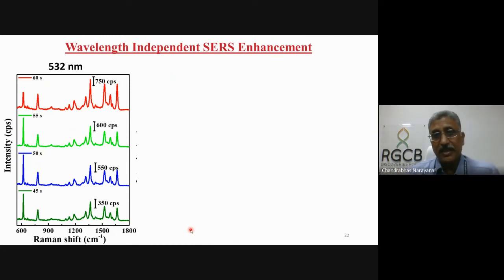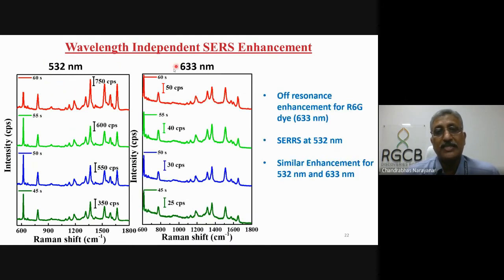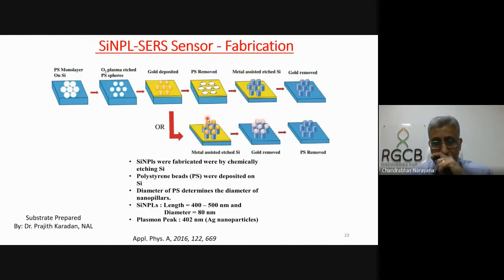The interesting effect is that it is independent of the wavelength of light. So we could actually do it with 532 and 633 nanometers, equally giving you very good enhancement for most of our samples. But we were not satisfied because it was giving enhancement only in the visible range. What we wanted is Raman in all ranges.